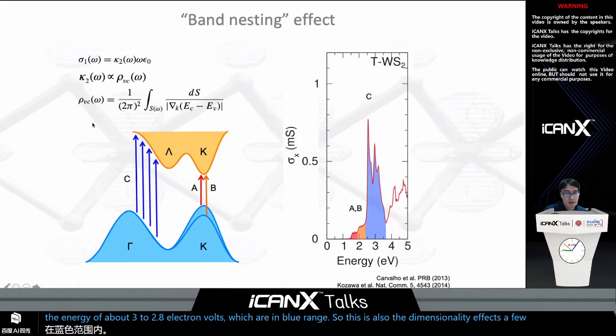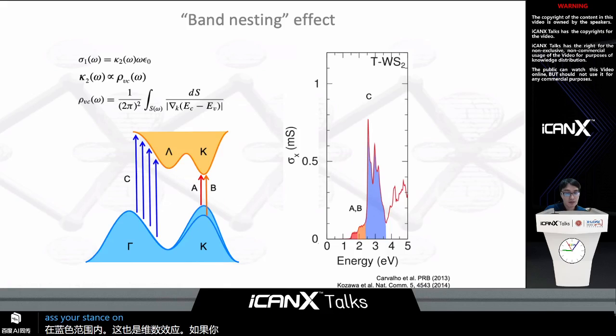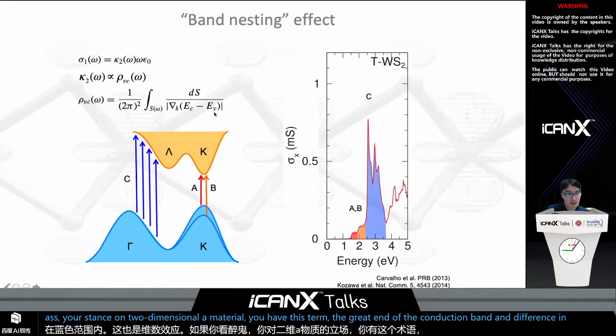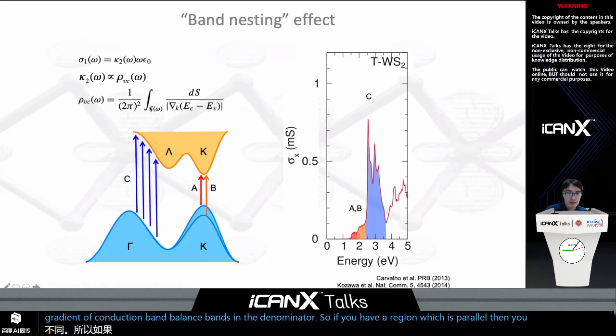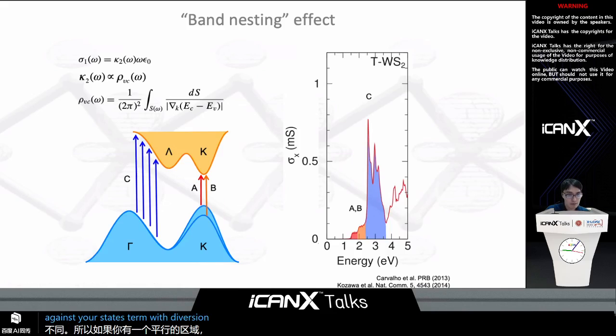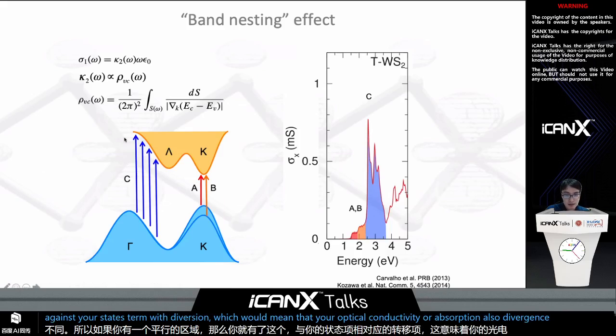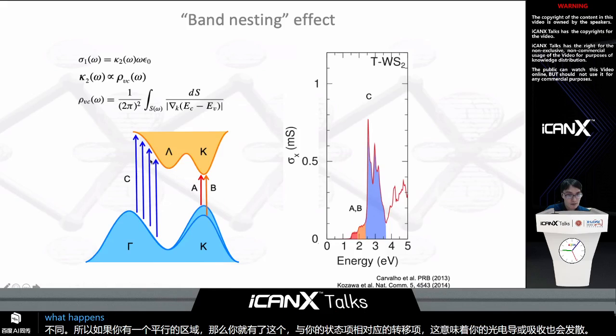If you look at the joint density of states of a two-dimensional material, you have this term, the gradient of the conduction band and the difference in the gradient of the conduction band and valence band in the denominator. So if you have a region which is parallel, then this joint density of states term would diverge, which would mean that your optical conductivity or absorption also diverges. And this is what happens for many of these two-dimensional semiconductors, particularly group 6 TMDs.